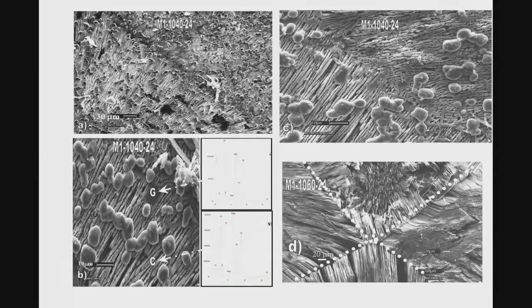Interestingly, when these materials were ceramized for 24 hours at 1060 degrees Celsius, I describe this morphology as envelope-like crystals, like a postal envelope. These crystals essentially have 4 different domains, and in each domain the straw-like crystals are oriented in a particular orientation, and this orientation differs. There is a clear transition at the domain boundary, which is shown here by the dotted line.